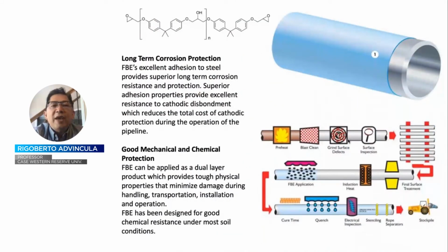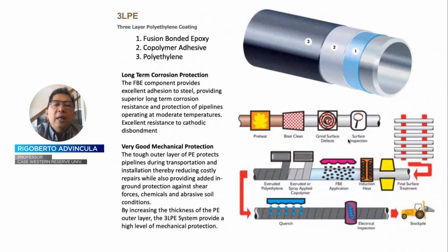So for example, here you can see how FBEs can be prepared on a steel pipe. Essentially, the FBE is applied with the heat or heated pipe. The FBEs are epoxy cured coatings. So you have epoxy and the heat together with the hardening that is introduced, resulting in a very durable coating that can be even applied in the interior of a carbon steel, meaning FBEs can actually be used to mitigate corrosion inside the pipe, or the insertion of liners or pipe within a pipe sometimes are employed to give a higher durability against corrosion. For example, other types of polyethylene and outer protection coatings other than the pipe itself can be used to expand the durability of these pipes on the field.